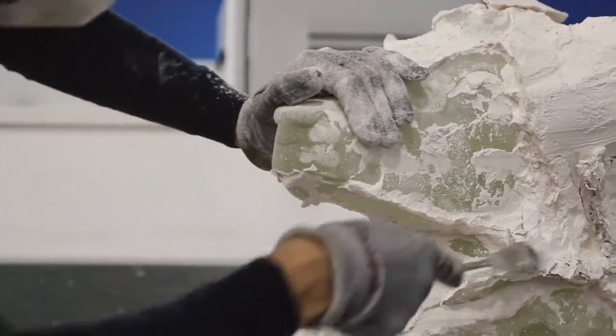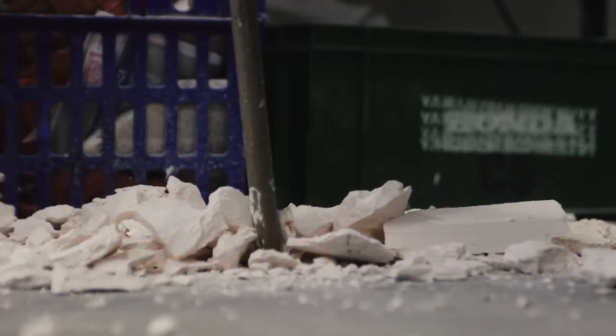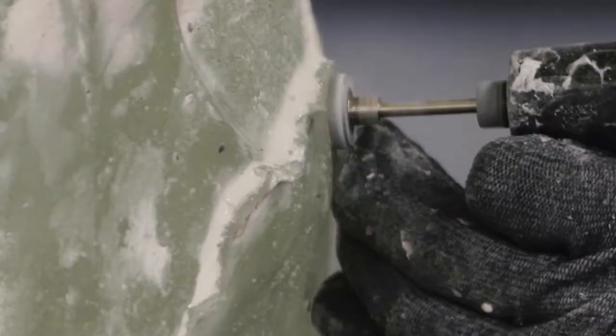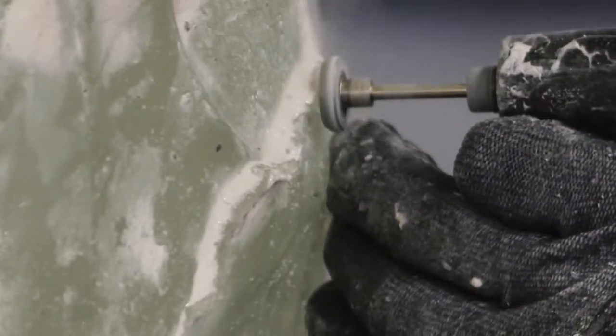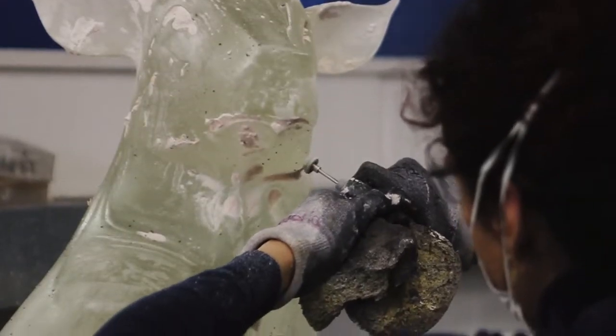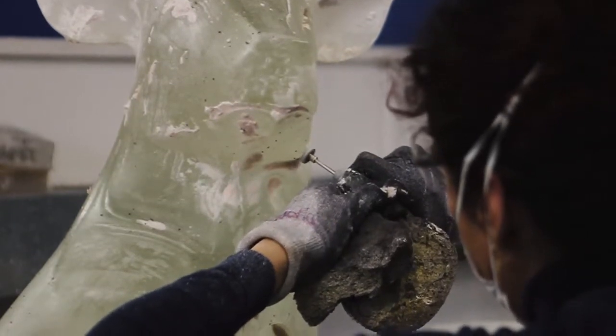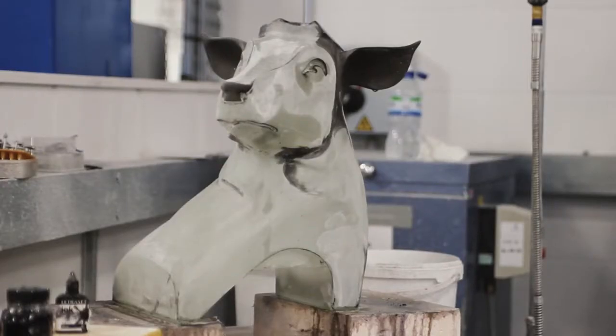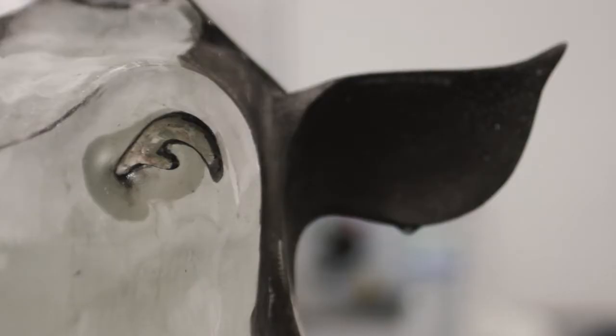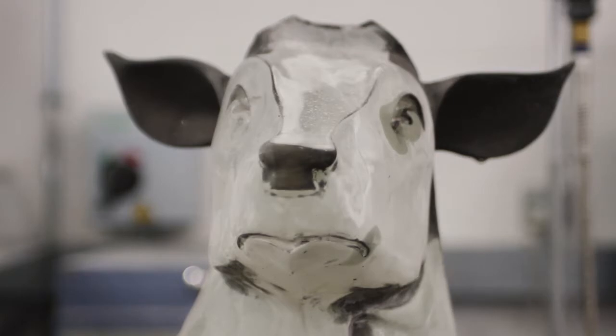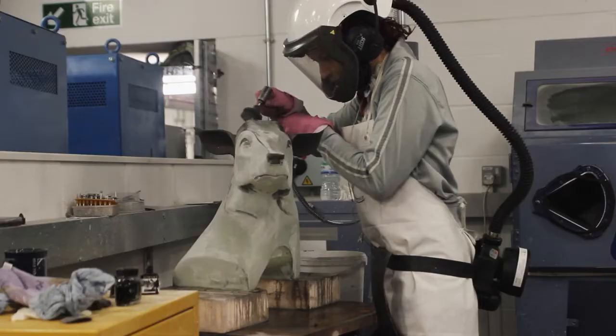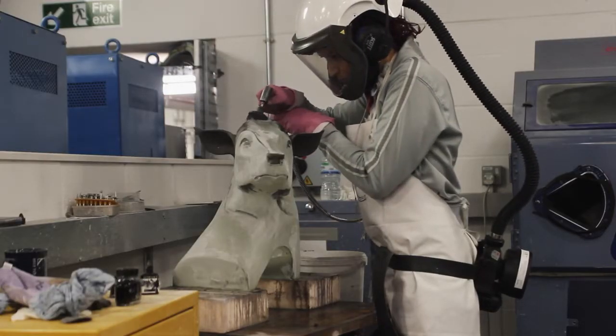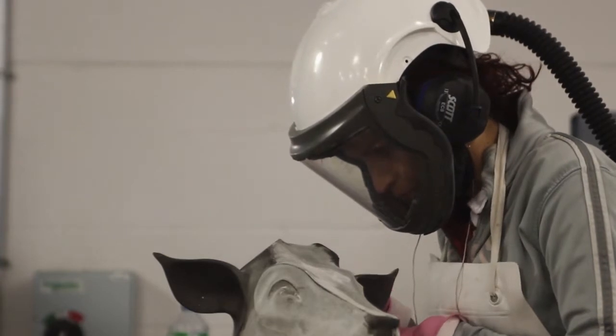So if there's any flashing, and there normally is a bit of flashing, I won't damage the object itself. The first thing I do once I've finished demolding and cleaning the stag is to take a marker pen or Indian ink and to paint the stag all over. So when I start grinding it, I will know which part of the stag have already been ground. The stag itself takes about 4 to 5 days to grind.